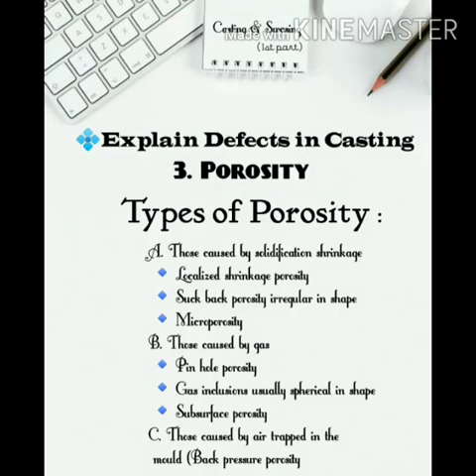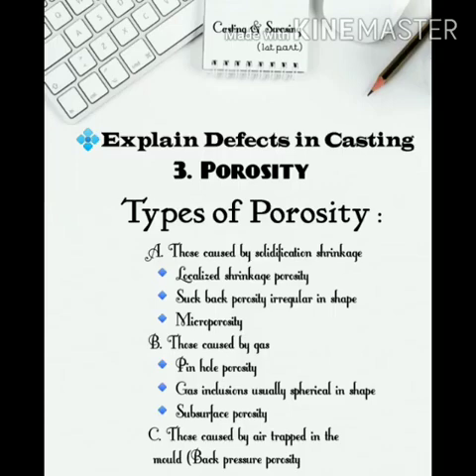Types of porosity: A. Those caused by solidification shrinkage: 1. Localized shrinkage porosity. 2. Suck-back porosity, irregular in shape. 3. Microporosity. B. Those caused by gas: 1. Pinhole porosity. 2. Gas inclusions, usually spherical in shape. 3. Subsurface porosity. C. Those caused by air trapped in the mold: Back pressure porosity.